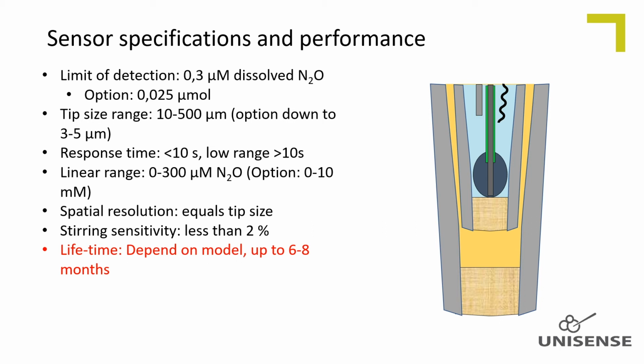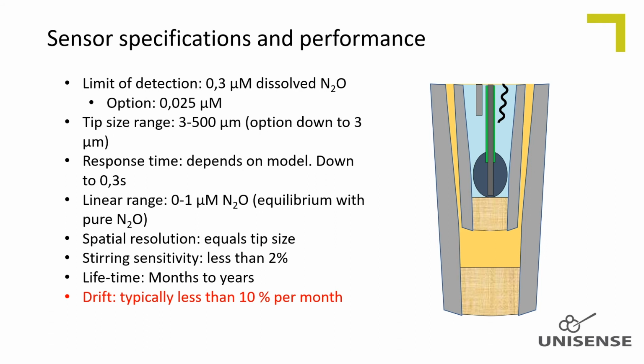The version we sell for wastewater monitoring is sold via our sister company, Unisense Environment, and this is made with similar long membranes. The lifetime is not dependent on how much it is used, it is simply a function of time. The profiling sensors with a faster response time have short membranes and therefore an expected lifetime of no more than 3 to 4 months. Nitrous oxide sensors are among the most stable sensors I know of.